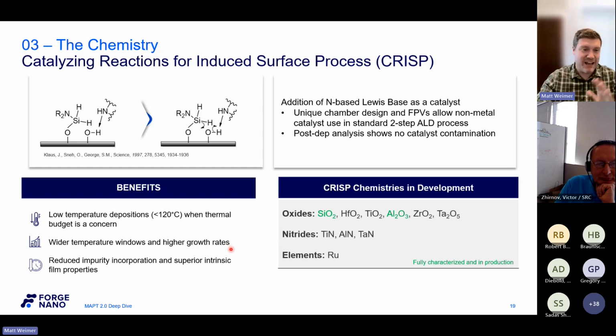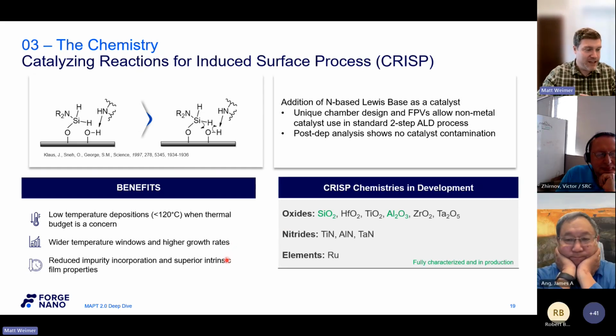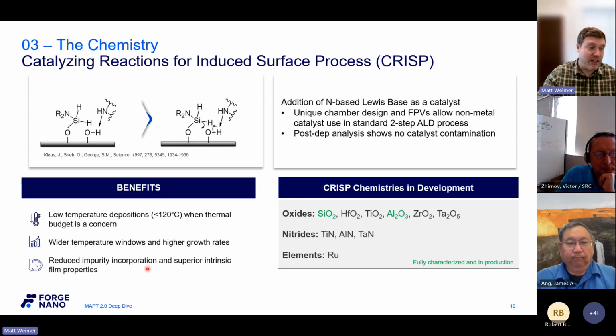One of the things that I've talked about indirectly, James, I'll get to you in just a second, is that reduced impurity normally shows up as a higher film density, and that knocks on to better film properties. So for silica, think about dielectric constant or breakdown voltage or leakage. All right, go for it, James.